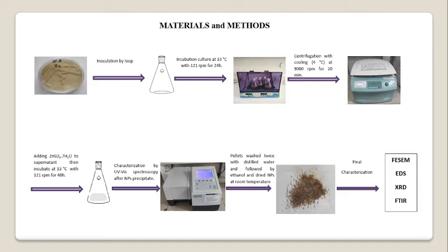Materials and method. This is a diagram that shows the activation of bacteria on nutrient agar after incubation for 24 hours. The nutrient broth was cultured, inoculated by loop, and incubated at 33 centigrade with shaking for 24 hours. After incubation, centrifugation with cooling was done at 9000 rpm for 20 minutes. After separation, the supernatant was mixed with zinc sulfate heptahydrate and incubated at 33 centigrade.